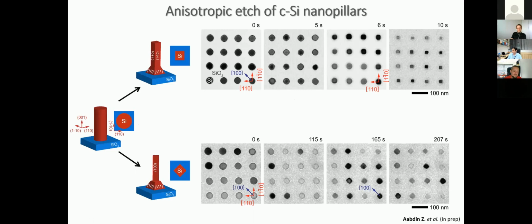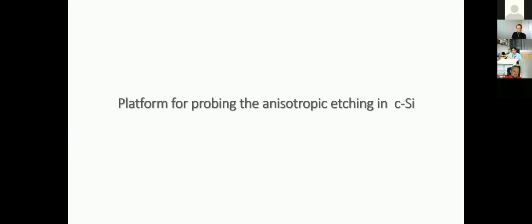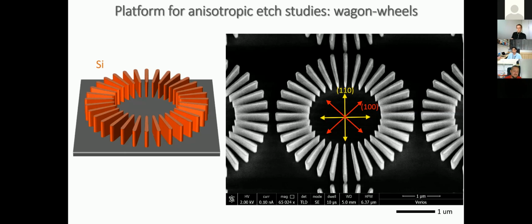Here we are all looking at the nanowires, and we only see a very limited number of the etch directions. Can we really build this into a platform where we can not only look at the 110 and 100 direction, but we can gradually probe between different etch planes? Well, how can you do it? You build this thing called a wagon wheel, right? So each face of this wagon wheel has a different crystal plane, and as you go around it, you can see that you have access to all the different crystal planes.